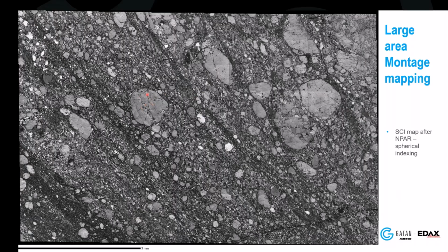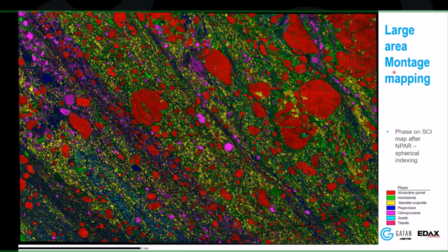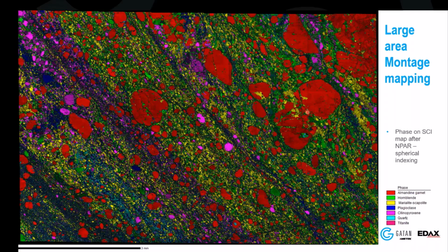Deformation inside the grains. And of course, we can see again all this fine grained material around here. Again, look at the scale of this thing. So this is basically a full thin section all the way across and up. So again, using both NPAR and spherical indexing, we're able to get these relatively high quality, large maps over these incredibly large areas. And again, this is something that is becoming very routine. Again, I mean, we're nailing every single little tiny grain in here.